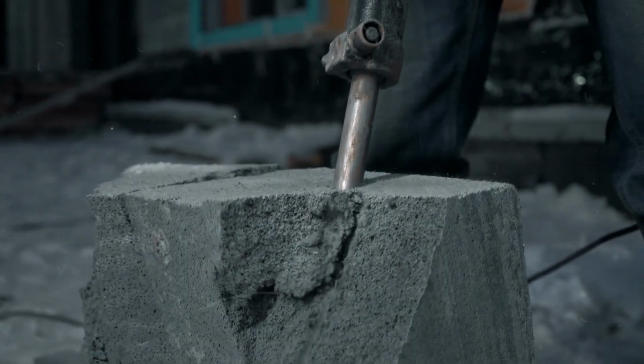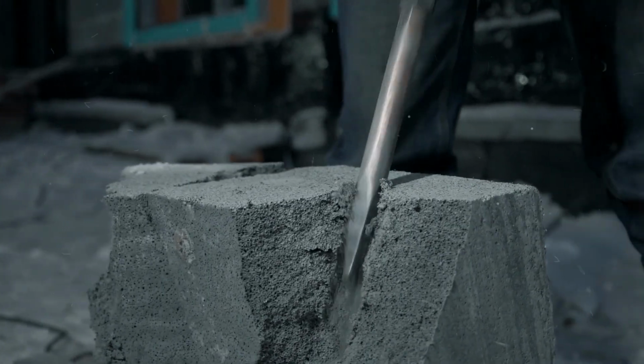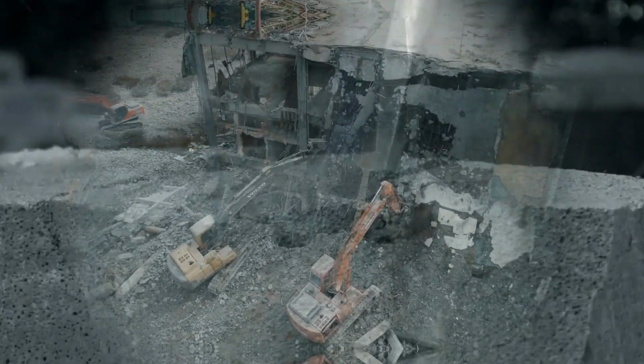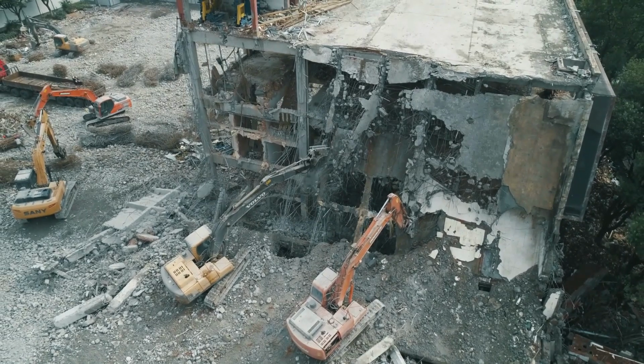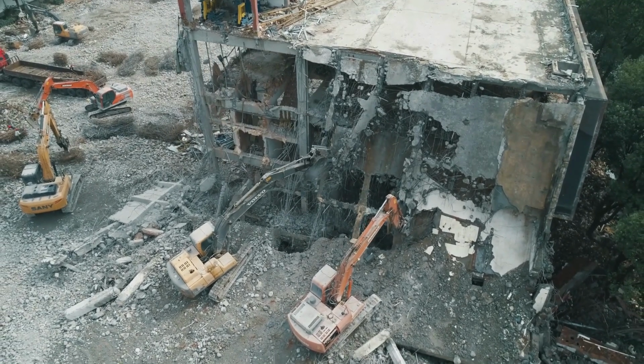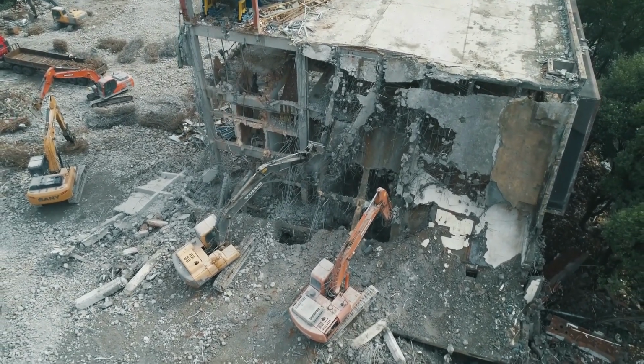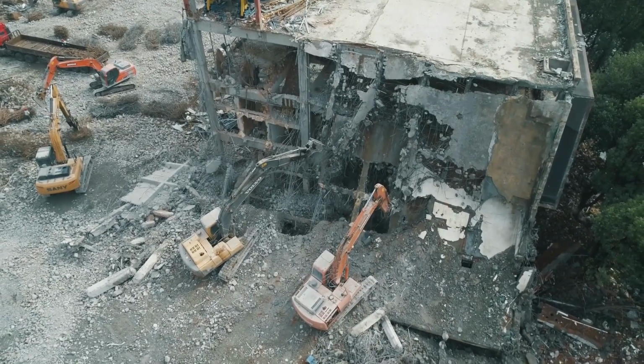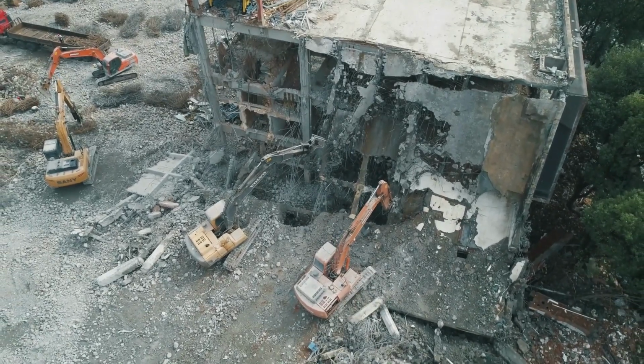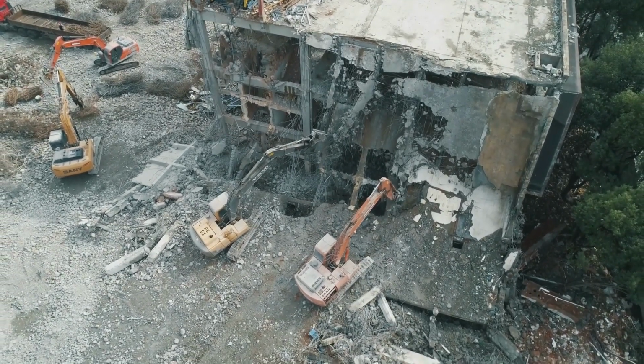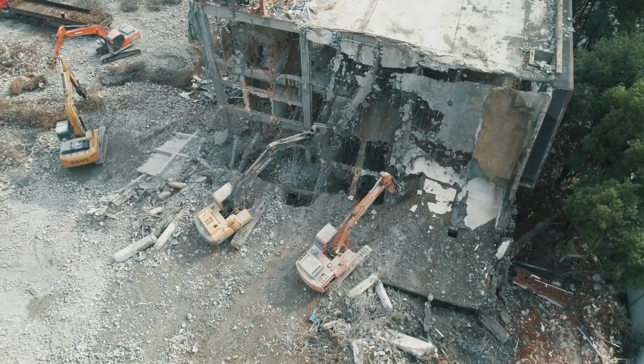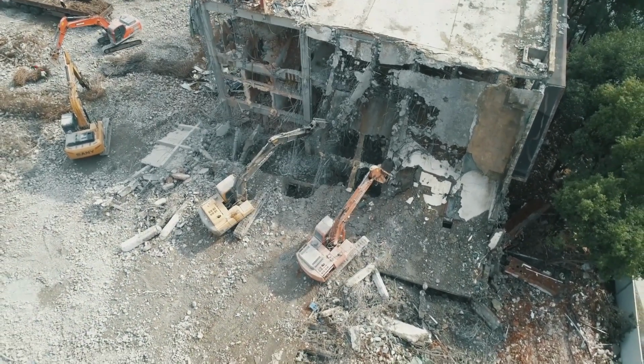No expensive additives, no exotic supplementary materials, no reformulation of the basic recipe that the industry has been using for 100 years. The same sand, the same aggregate, the same cement, the same water, handled differently for approximately 10 to 15 minutes, produced a material that was fundamentally and measurably better by every standard metric the industry uses to evaluate structural concrete. What happened next was almost as unusual as the results themselves.